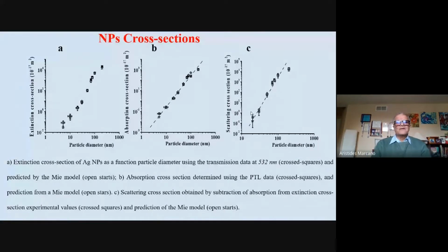This is one interesting thing. We just measured the cross-section of the nanoparticles in total. So I have the extinction cross-section, which includes the scattering part and the photothermal part, which here is called absorption. So the extinction has these two parts. And you see that because I have the size of the nanoparticles. I have nanoparticles that are 100 nanometers and 200 nanometers, and I can get this spectrum.